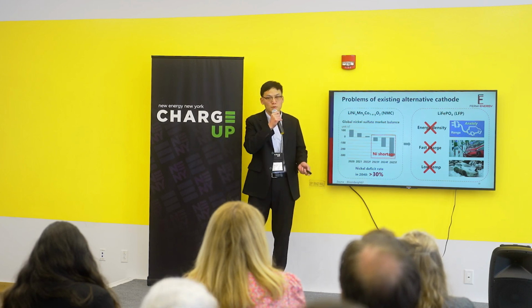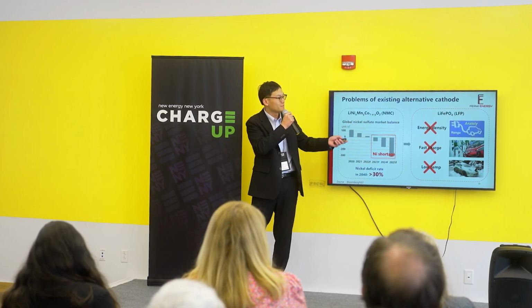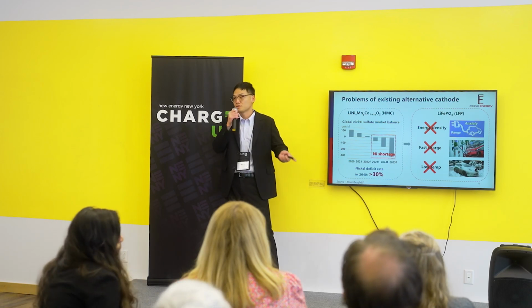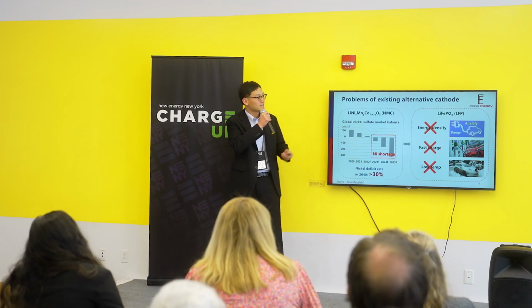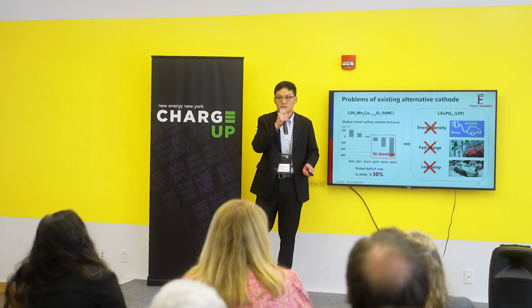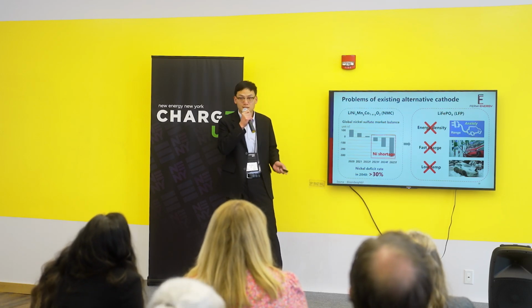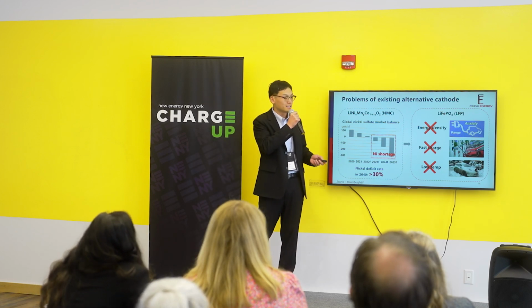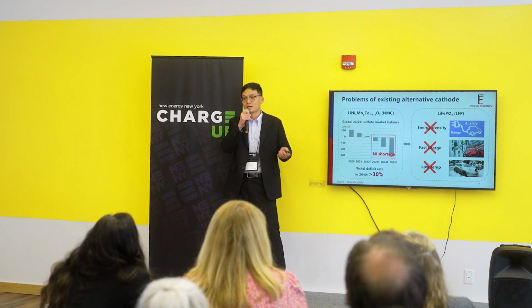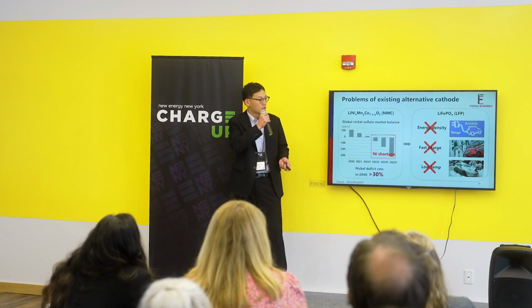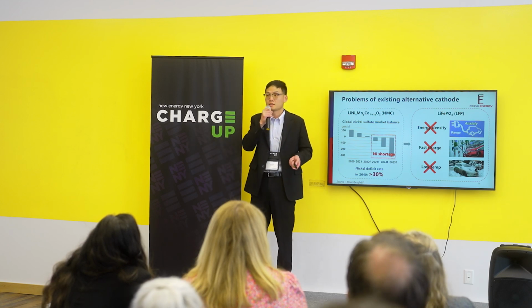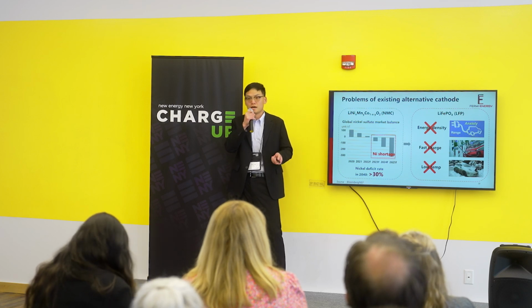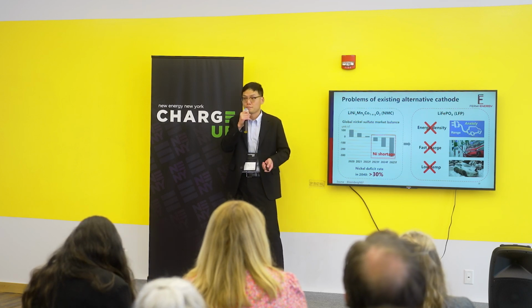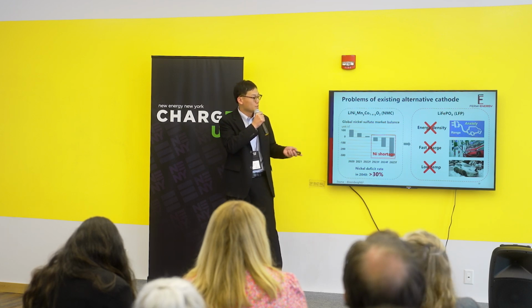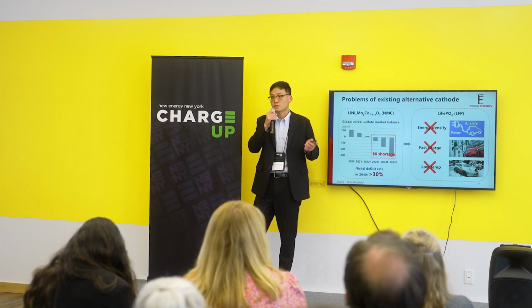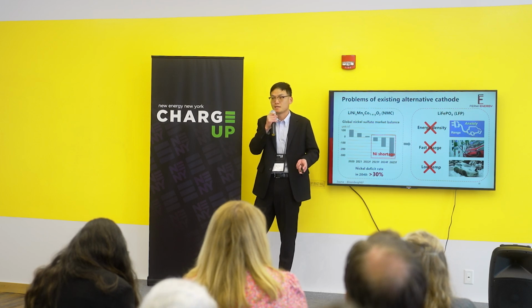If we don't use nickel and cobalt, we actually have other chemistries, such as lithium iron phosphate. To be honest, this chemistry is great. It has really stable cycle life, really good for EVs, but it has three intrinsic problems. One being lower energy density, meaning that for typical EV charging, you can drive less than 300 miles. The second one being the fast charging capability. LFP chemistry typically cannot do fast charging because of the chemistry itself. And the last one being really poor low temperature performance. In winter time, you can maintain less than 50% of its capacity.